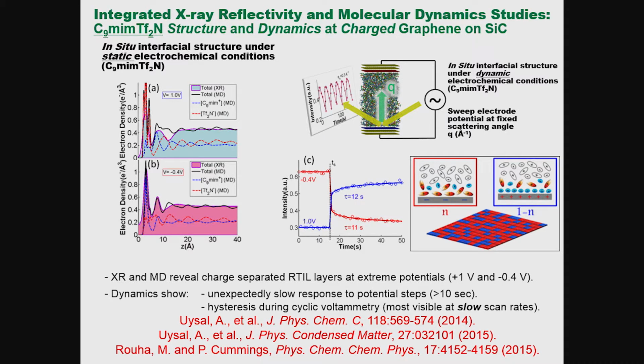This was work that Ahmed talked about yesterday, looking at the structure of ionic liquids at this graphene on silicon carbide interface using X-ray reflectivity. This is an example of the density profiles away from the graphene surface at +1 volt and -0.4 volts. The purple is the total computed electron density.